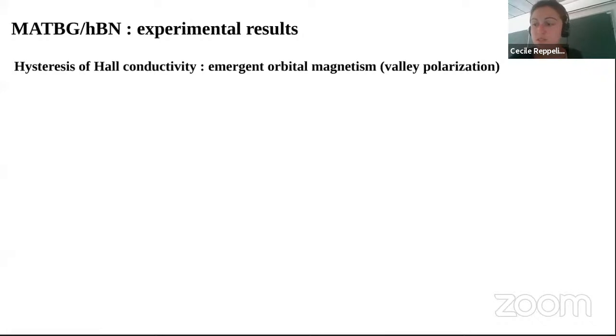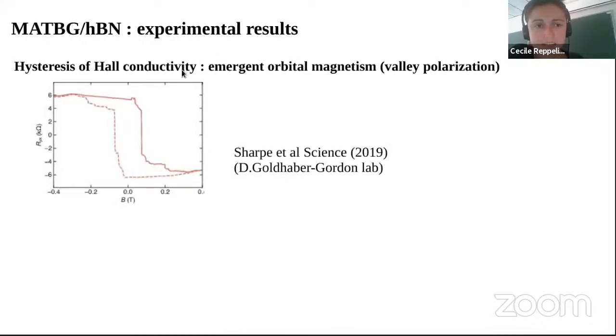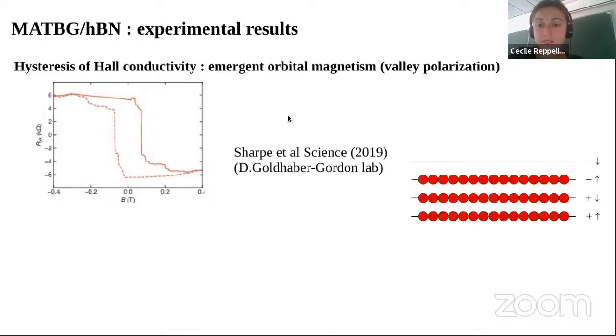So let me start with a few experimental facts. Magic angle twisted bilayer graphene aligned with HBN has been realized before. And this is what is seen in various experiments. So first of all, there's a hysteresis of the Hall conductivity, of magnetotransport in general. And this hysteresis indicates an emergent orbital magnetism. This data is from David Goldhaber-Gordon's group. And this was the first time that this emergent orbital magnetism was found, and it was found for filling 3, meaning that in mean field this would correspond to filling 3 bands out of 4 in the conduction band.